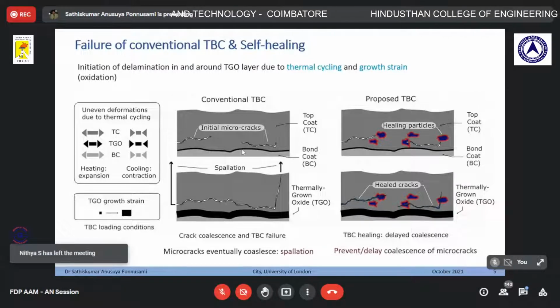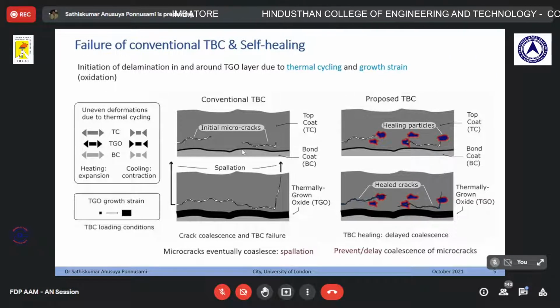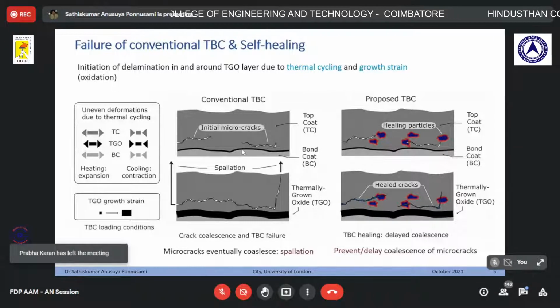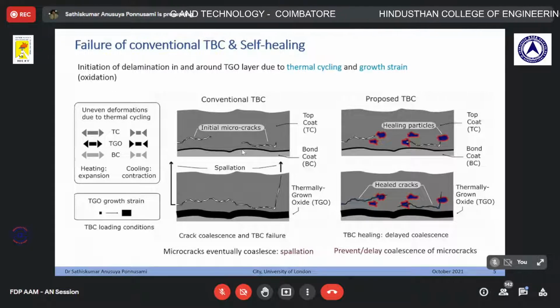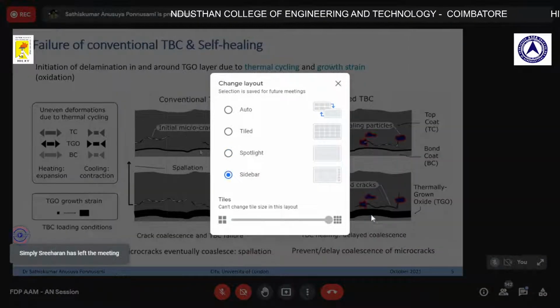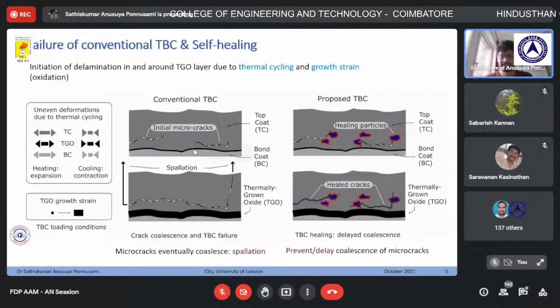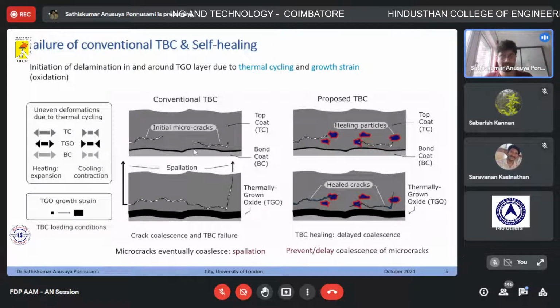Okay, and through our experimental testing with computational design, we were able to achieve a 30% increase in the lifetime of the thermal barrier coatings. Okay, and that is quite significant. 30% might seem a bit little, but it is quite significant for the aeronautical industry, because these maintenance operations, or rather repair operations, are not only costly, but also have downtime, engine downtime. You cannot fly, of course, without the engine, isn't it? So it all adds up to easily several hundreds of thousands of pounds or euros, depending upon where you are, for each carrier. And if you add that for the entire world, you can calculate the amount of cost and time, human time, and downtime as well.